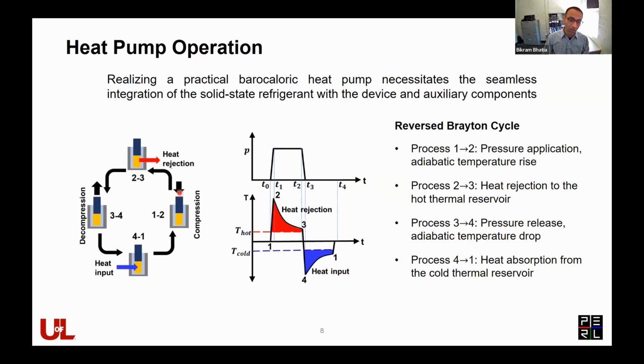So you basically have a four-step cycle where you compress the barocaloric material, which results in an increase in temperature of the barocaloric material. You interface it with the hot side, and you reject the heat, and then you release the pressure, which results in a sudden drop in temperature, and then you interface it with the cold side heat exchanger or cold side reservoir, completing the cycle. So you can go through this cycle several times and basically have a functional heat pump.